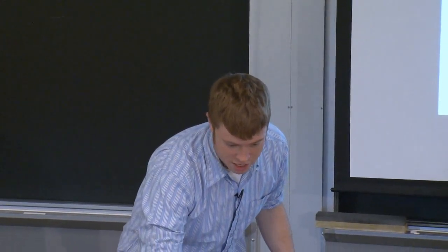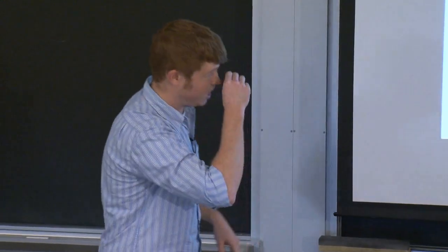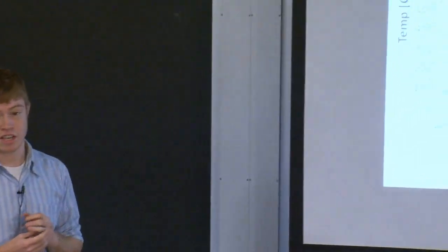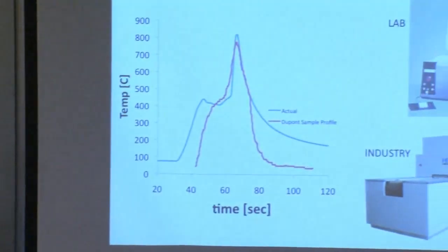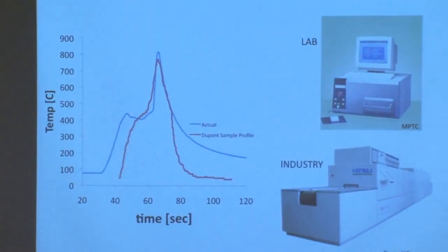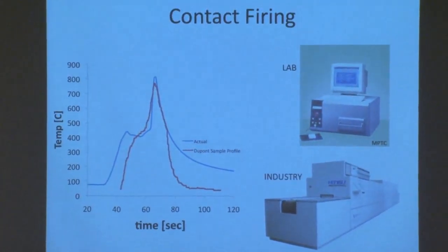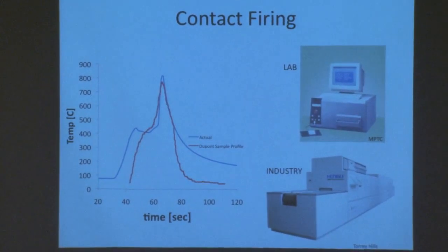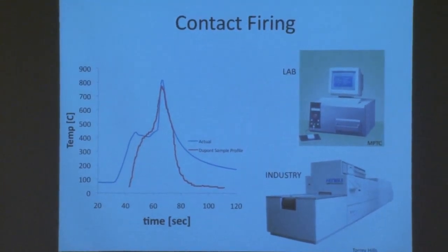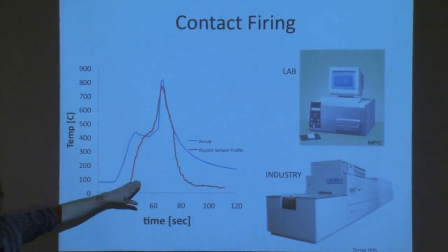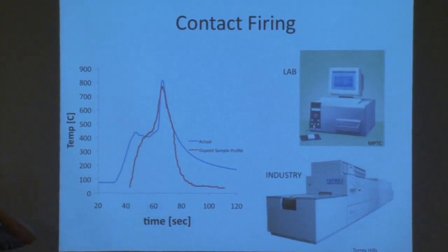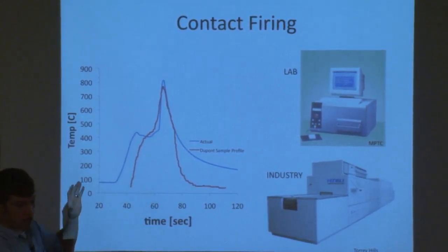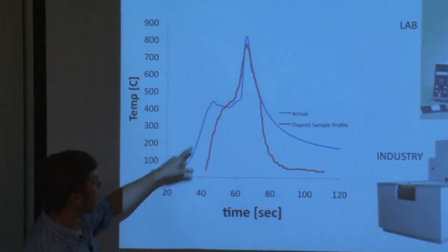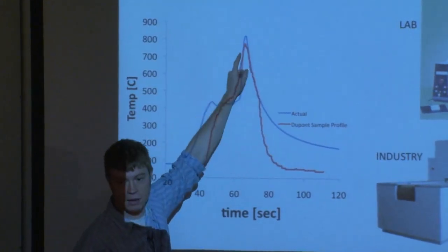But just to give you guys the processing that you didn't get to see, this is what the contact firing looks like. It's a very, very fast process. It's really remarkable to me that it combines so many photolithographic steps, condensing 6 or 7 steps into one process that in the lab using photolithography would take much longer. So DuPont, the people who made the paste, we use PV16A, if you're curious, for our front contacts, the silver paste. The really important part is this peaking temperature.